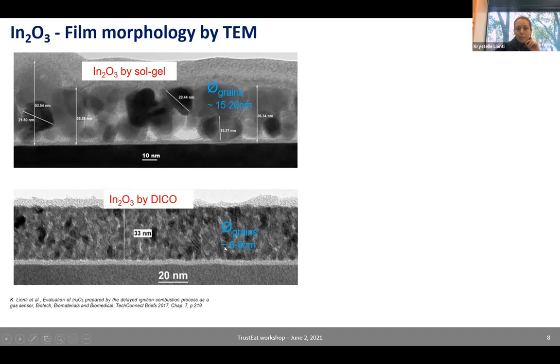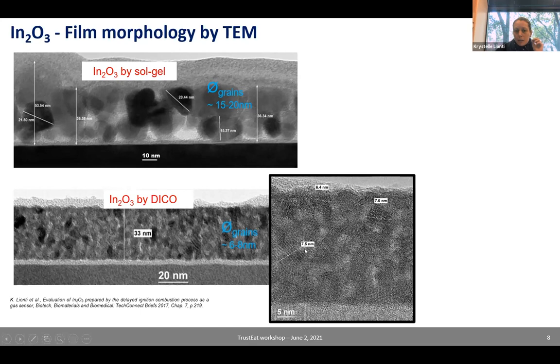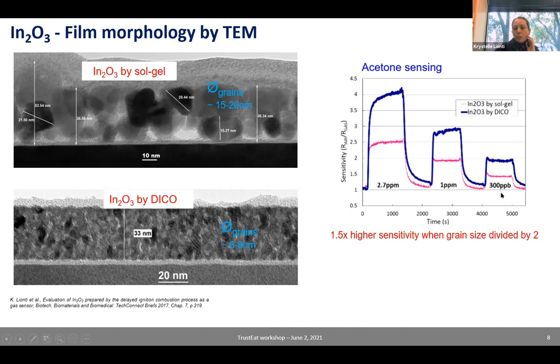6 to 8 nanometers for the DICO process that we can see here by TEM pretty nicely, or 15 to 20 nanometers for Sol-Gel. So again, very small grain size in both cases, but we do have a 2x difference between these two films. And when we did some sensing experiments using acetone in pretty low concentrations, we saw systematically a 1.5 times difference in sensitivity between these two films, with the higher sensitivity being obtained for the thin film with the smallest grain size. So grain size is definitely very important, and it's good to minimize it to boost the sensor sensitivity.